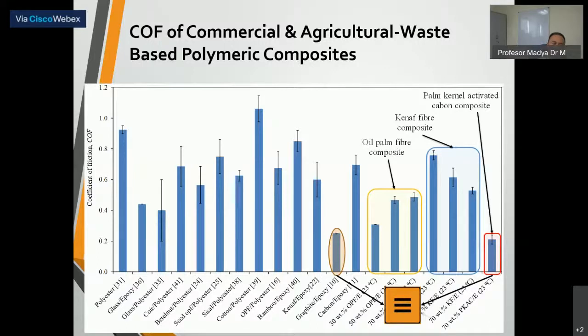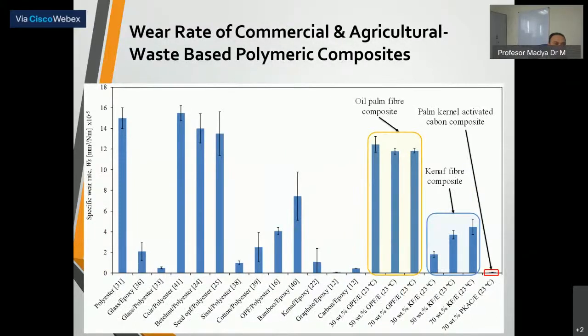Above 0.2 or 0.3, because we test under dry conditions, and when we test under lubricated or water conditions, the coefficient of friction can be as low as 0.1. Okay, this is the wear rate. We can see that the wear rate of palm kernel activated carbon is the lowest among other agricultural waste-based polymer composites and also the commercial composites. We can see again the wear rate is also similar to graphite.